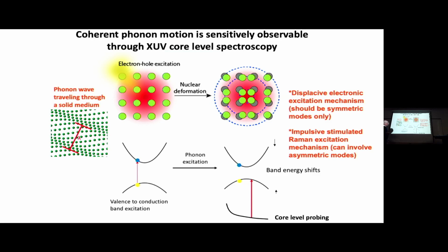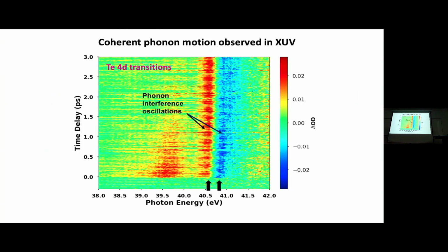And there could be two mechanisms that Millie Dresselhaus has told about in lots of papers initially. There can be a displacive electronic excitation, which is just this dramatic change in the bands, like this. It should apply mostly to the symmetric modes, the phonon modes in the lattice. Or there can be an impulsive stimulated Raman, where you pump up and pump back down again with a short pulse, and that can involve asymmetric modes. So these have been described, and they happen. Both of them kind of happen almost instantly, and then in addition, the hot carriers can feed this to do more.